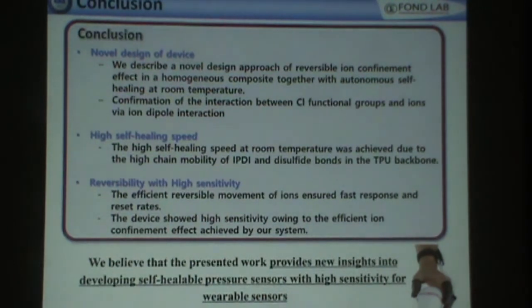So in conclusion, we have described here a novel design approach to achieve a reversible ion confinement effect in a homogeneous composite together with autonomous self-healing at room temperature. We are able to achieve this through the introduction of chlorine functional group together with ions via ion-dipole interaction. The higher self-healing speed was possible due to the high chain mobility of IPDI as well as the dynamic disulfide bonds in the backbone of the TPU.